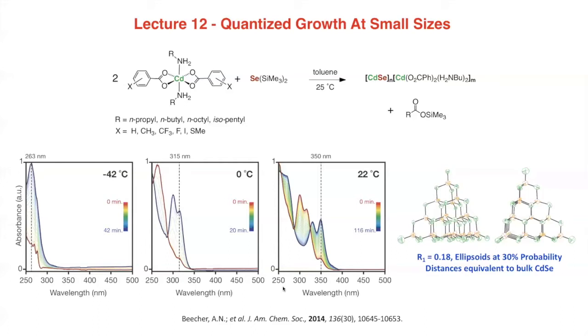The other thing about this data, which we're not going to talk about, but is a good thing to be aware of, are these very interesting crossing points. Notice how all of the spectra in here, there are many different spectra going from this time to that time, and they all cross at these points. These are called isosbestic points. And when you see them, it's an indication that you have two things interconverting.